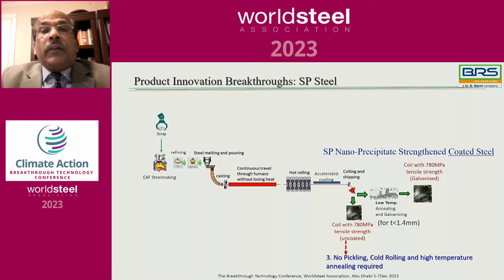This nanoprecipitate strengthened steel is obtained in the hot band coil with a tensile strength of 780 MPa. But if somebody wants it in the coated condition, this hot band coil can also be taken through a galv line with a very low temperature heat-to-coat annealing cycle that can coat the steel without affecting any mechanical properties or formability properties.